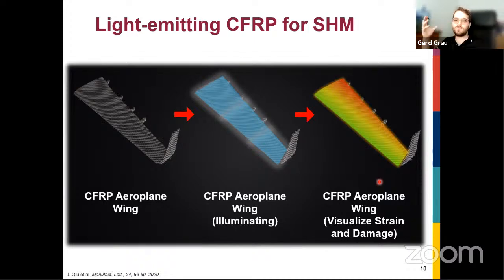So imagine you have a carbon fiber structure and you want to know, is there a lot of strain in the structure? Where do we have strain? Or do we have damage somewhere? So maybe there's a crack forming, a fatigue crack that if you catch it early, you can do maintenance or maybe change the part before there's a catastrophic failure. If you have a light emitting structure where if the light goes out in a certain region, you can tell I have to do maintenance, then that makes monitoring much easier than if you actually have to go in and measure in detail if there's any damage anywhere. This can be done with a simple camera, for example.